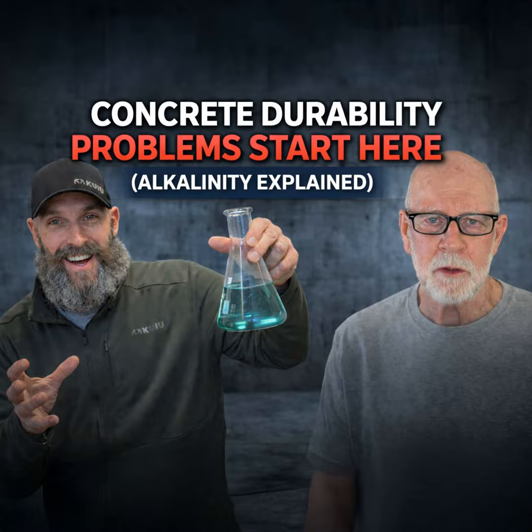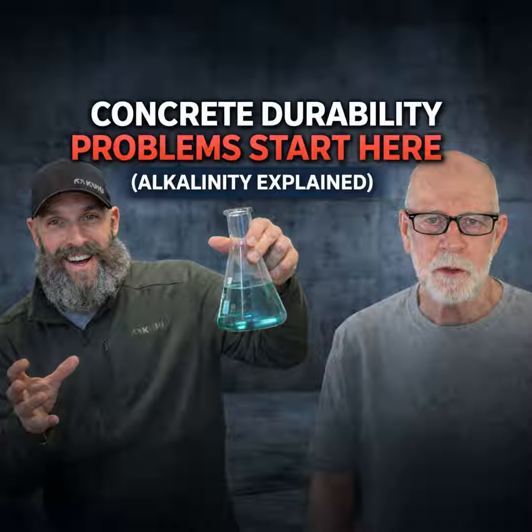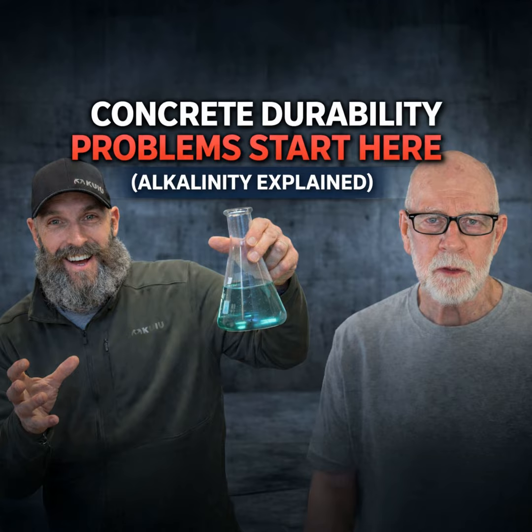So they could actually see it. There's a roadway that had hit the compressive strength that was specified, and the one that didn't was actually performing better. Well, if they weren't allowed to use it, how did they know that the one that didn't hit the compressive strength was doing better? Well, everything around it was falling apart. They did an experimental test section, but it didn't meet their minimum compressive value, so they rejected it. But there it is, holding up year after year. That pavement was about 20 years old when I saw it, and there were roadways around it that were less than 5 years old that had extensive damage from freezing. Those met compressive strength and exceeded compressive values.